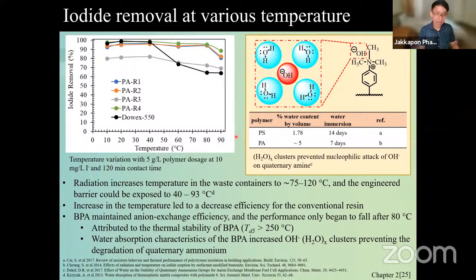That's the first thing. And the polyamide itself has a very high water content by volume. Why is high water content important? Because it acts like a barrier against polystyrene or polymer degradation. In adsorption, sometimes you want the polymer to be able to absorb water when it does the adsorption, and this is the case that it needs, okay?